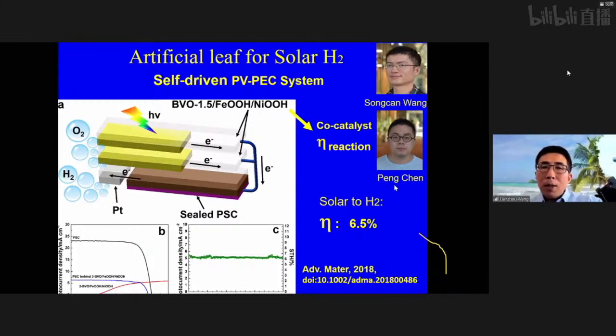But if you think about the solar to hydrogen conversion target, we still have a long way to go. If you look at this curve, the solar cell can produce relatively high photocurrent. This is the working point, which is related to the efficiency of 6.5%. If we really want to further increase the efficiency for solar hydrogen production, we really need to push higher on this side, this red curve. This red curve is related to the photoelectrode we developed.